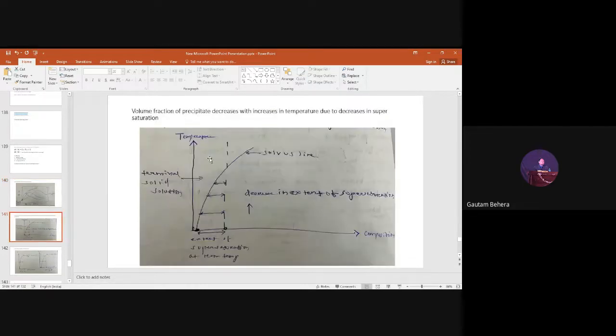Now you can see this is a very interesting figure where we can see the volume fraction of the precipitate decreases with increasing temperature. Right? As I told, for the same volume fraction of precipitate, the size of the precipitate will become more, but the volume fraction is decreasing.